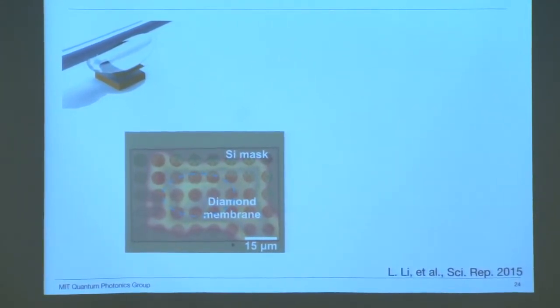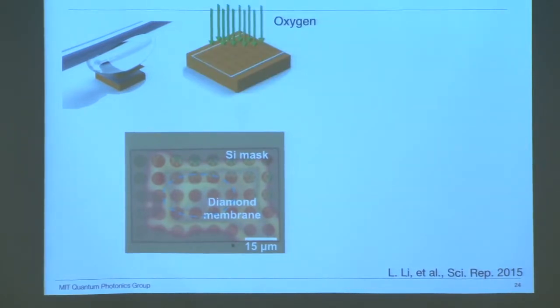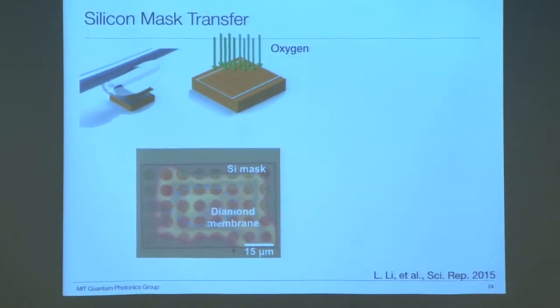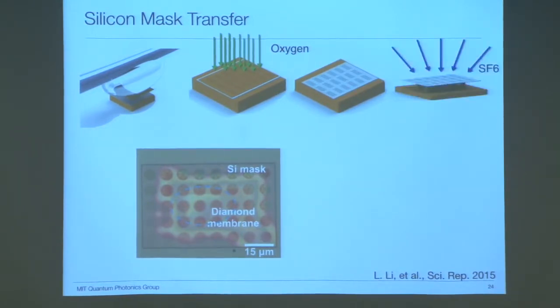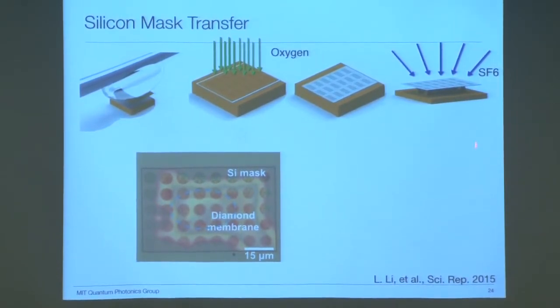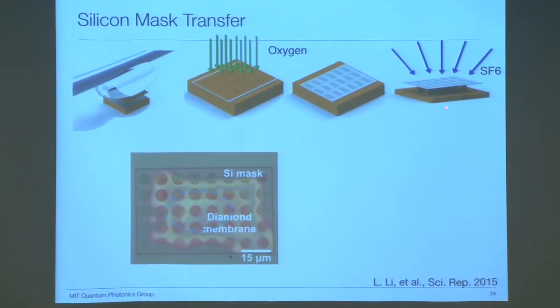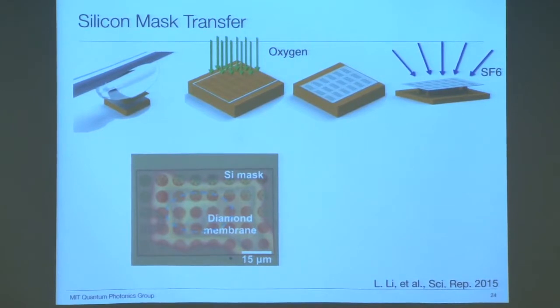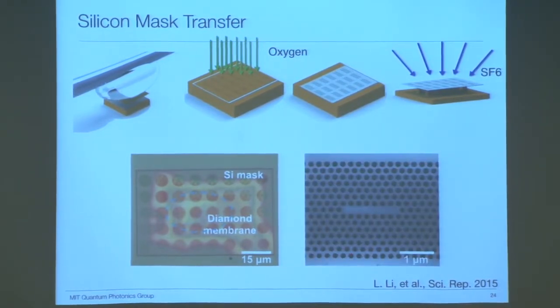The diamond membrane has a much smaller size in natural dimension. We use oxygen plasma to transfer the pattern from the silicon mask into the diamond membrane. After removing the silicon mask, we use SF6 plasma etching to lightly remove the silicon underneath and suspend diamond photonic devices at device locations. This is an SEM image of the resultant photonic device. It happens to be a two-dimensional photonic crystal cavity with 7 missing holes to form a resonance. This method is not limited to this specific pattern. It can be used for any patterns as long as they can be prepared in a contiguous mask.